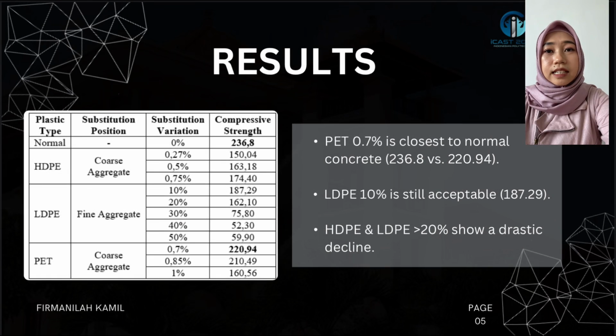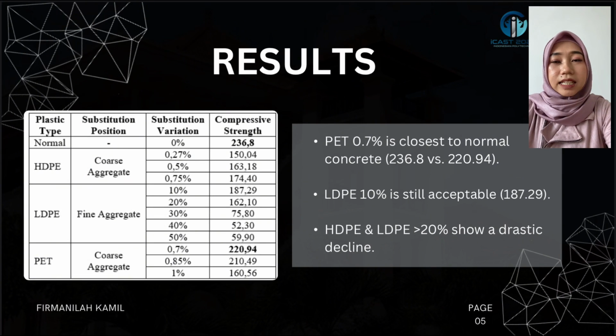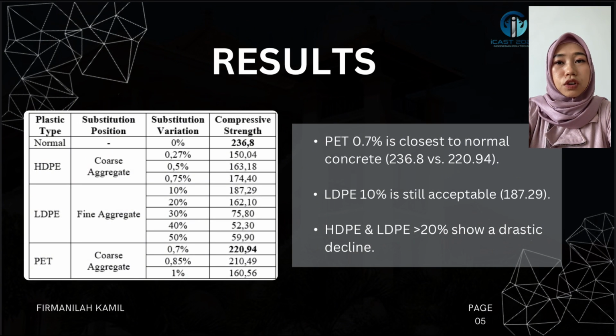Now, let me present the results of our study. Based on the compressive strength test, we found several important findings. PET at 0.7% substitution showed performance that is closest to normal concrete, with a compressive strength of 220.94 kg per square centimeter, compared to 236.8 kg per square centimeter in the control sample.